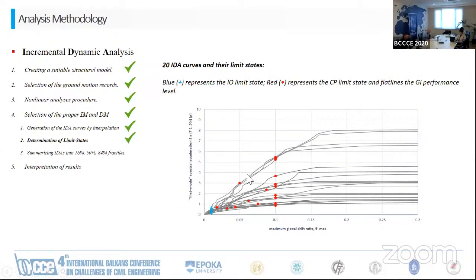The next step is to define all the immediate occupancy points. As you can see here, we have defined them by the blue cross, and also the collapse prevention. As you can see from the graph, some of the collapse prevention points have been defined at 10% of damage measure because the 20% slope has not appeared yet. So this might be the boundary, the ultimate limit of the collapse prevention. For the other ones, we are selecting the 20% of the elastic slope. And then the flat lines represent the failure of the building, which is also the global instability limit state.